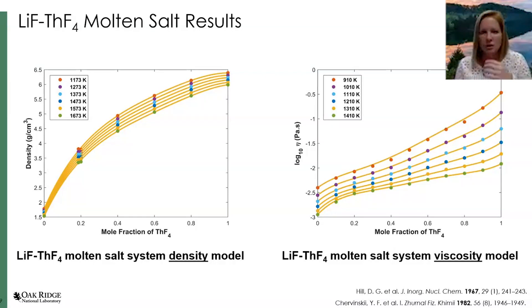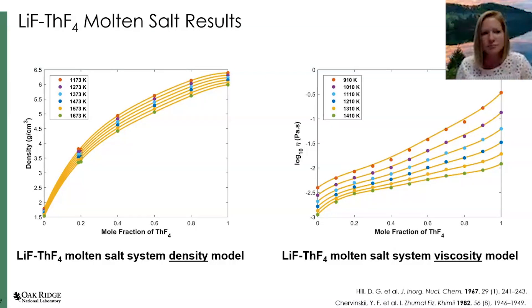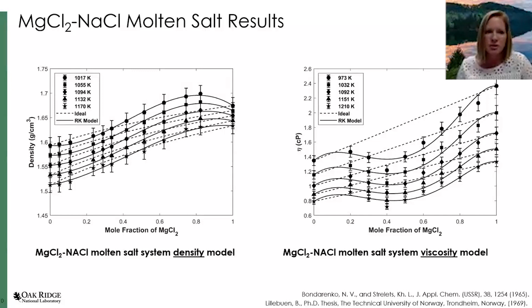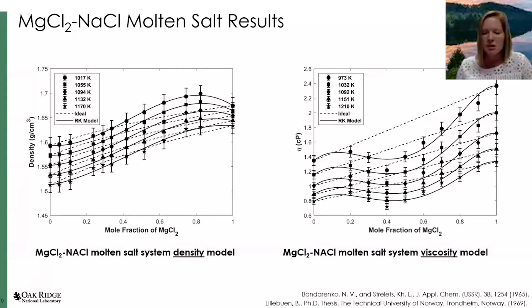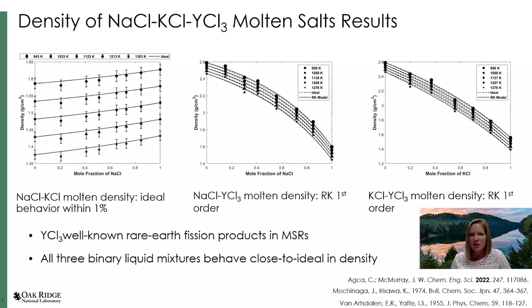This is how we build into complexity. Another example is the magnesium chloride, sodium chloride pseudobinary. You can see the density and viscosity results shown here, purely based on data from literature. The dashed lines are the ideal solutions missing the expansion, whereas the solid lines show the data generated using the Redlich-Kister expansion with fit. So you can see it's just a much better fit overall.